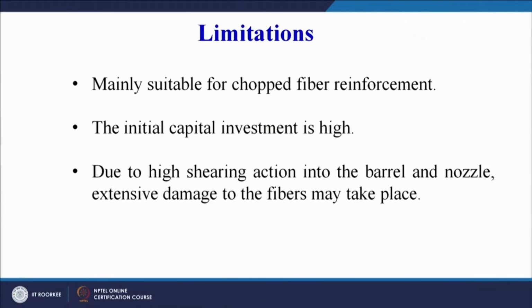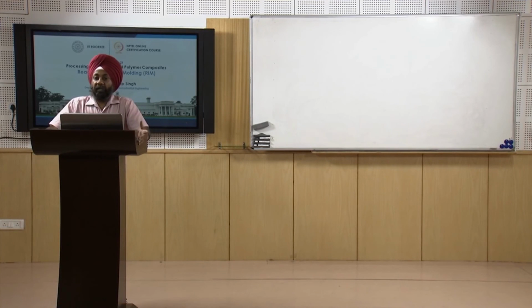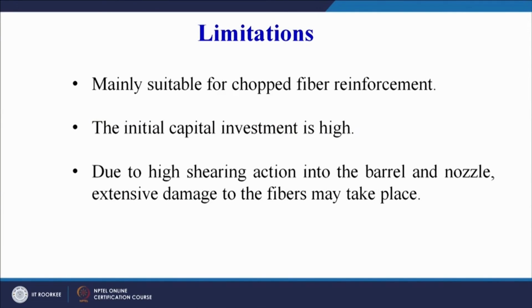What can be the limitations now? Mainly suitable for chopped fiber reinforcement, whereas the structural reaction injection molding can be used for woven mat type of fibrous reinforcement also. The initial capital investment is high, it may be higher as compared to the hand layup or the spray layup process, but will certainly be lower than the conventional injection molding process. Due to high shearing action in the barrel and nozzle, extensive damage to the fibers may take place, specifically in the case of the conventional injection molding process.